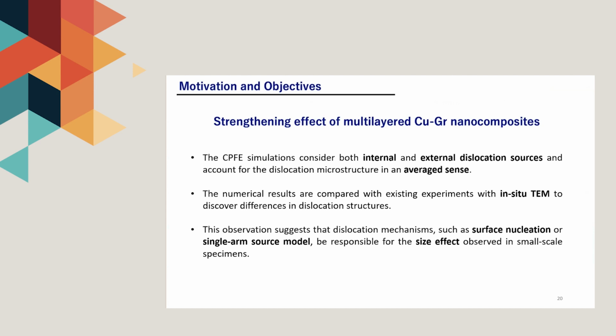The next example we're using is the strengthening effect of multi-layered copper graphene nanocomposites. In this case, we're using crystal plasticity finite element simulations, both internal and external dislocation sources, and account for the dislocation microstructure in an average sense.